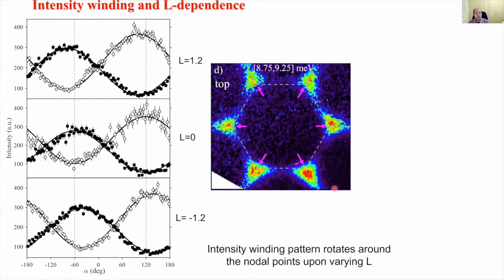Okay, so before that, let me explain in more detail the L dependence of this intensity modulation. So L is the vertical direction perpendicular to the layers. So if we pick one K point up here and do an azimuthal scan, then at L equals 0, the maximum is at minus 60, which corresponds to this radial direction here. However, if we go at negative or positive L's, this maximum shifts, okay? Which suggests that the maximum will be here for negative L and here for positive L. So this intensity distribution is twofold at every L, but actually it spins round as one moves along the nodal line.